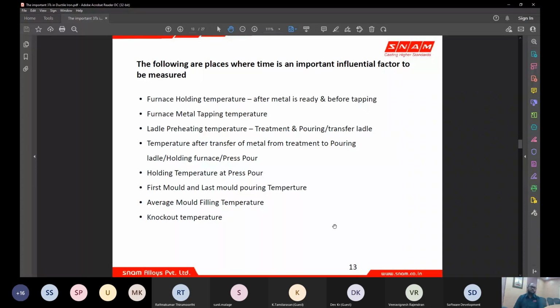So the first box casting and last box casting can be slightly different because of the temperature at which we fill. And as we have seen, the average mold filling temperature should be technically constant throughout the entire process. And the knockout temperature is directly related to residual stress, and also the phase transformation happening. So if you knock out the casting above 750 degrees Celsius, as we know the eutectoid transformation is going to happen at 723 degrees Celsius, which determines your pearlite content, the coarse or fine pearlite which is going to come. So when you knock it out very early, there is a tendency that your coarse pearlite can become fine pearlite also.